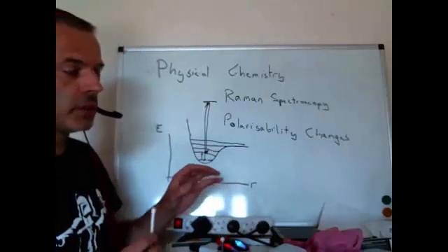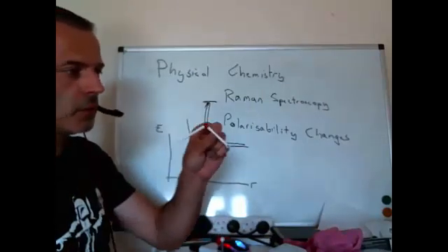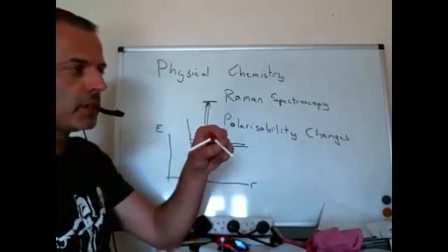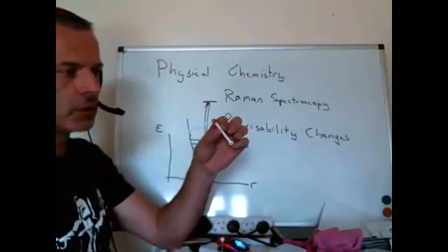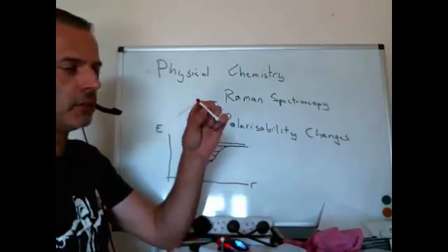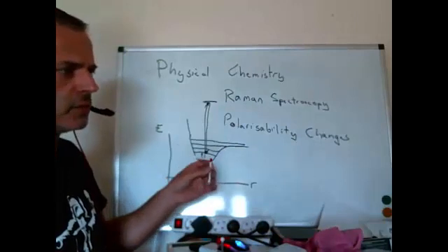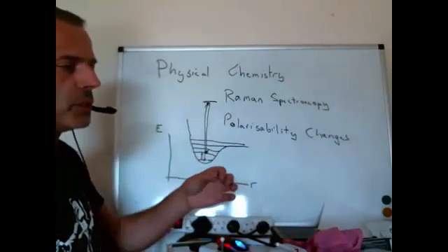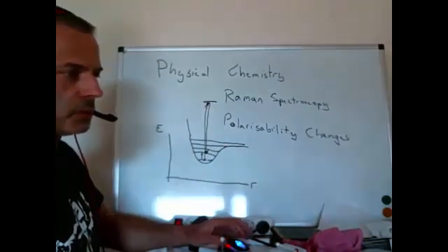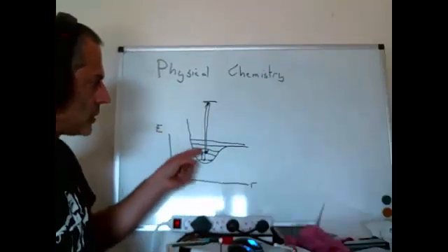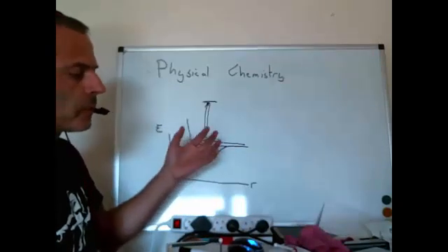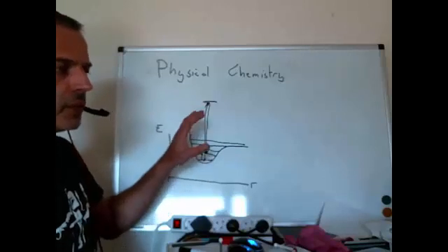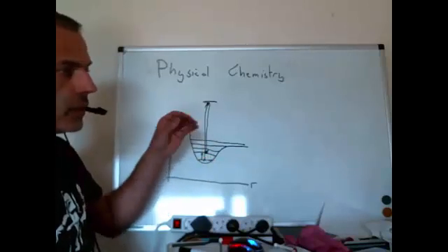What this means in practical terms is that we can measure a Raman spectrum of our molecule in water far more effectively than we can measure an infrared spectrum in water, because water is very, very absorbing in infrared and gets in the way of nearly every measurement that we want to make. If we want to make an infrared measurement, we typically try to make things as dry as possible. The probability of Raman scattering, where the energy comes out differently, is very low, as we just said, because it's quantum mechanically not allowed. It's very low, and therefore we need a lot of light to do it.